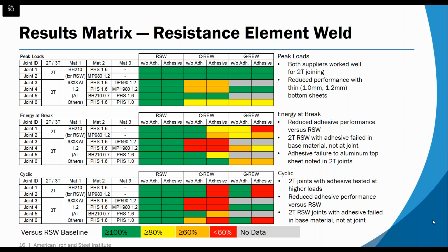We did see some differences in adhesive performance for energy absorption on the two-thickness joints in particular, and that was again because the failure mode changed. We broke the coupon at the interface to the joining element instead of separating the top sheet, so that is not unexpected.